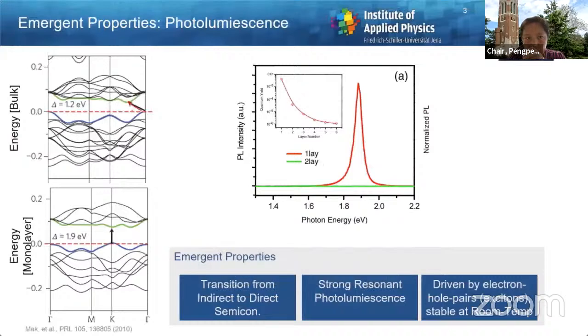from the energy band structure. You see this on the top here for the bulk, which is an indirect transition. At the bottom, you have a direct transition at the K point. And of course, this change from indirect to a direct transition enhances a lot of light-matter interaction effects rather drastically, as you can see here, for example, from a photoluminescence spectrum. So you excite your material with short wavelength light. And then if you have a monolayer crystal, you observe this nice and very strong photoluminescence in the red, at 670 nanometers, as opposed to a two-layer crystal, where this photoluminescence is very negligible. And this photoluminescence is driven by electron hole pairs, which are frequently called excitons.